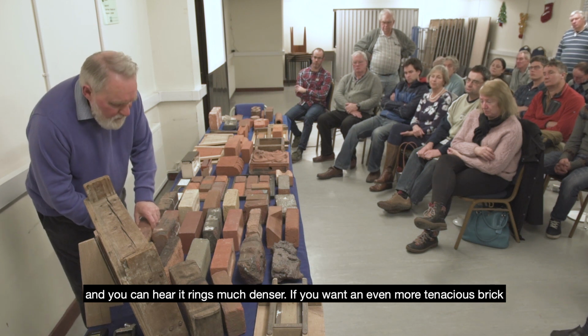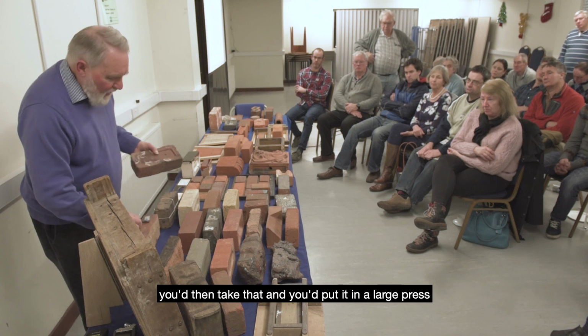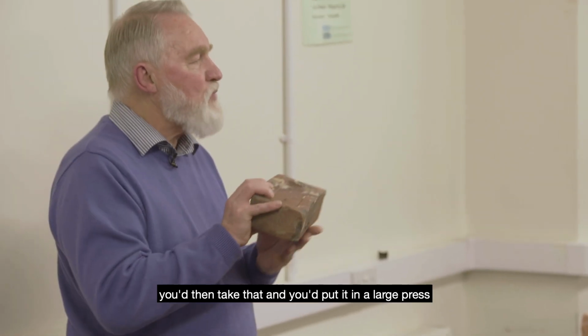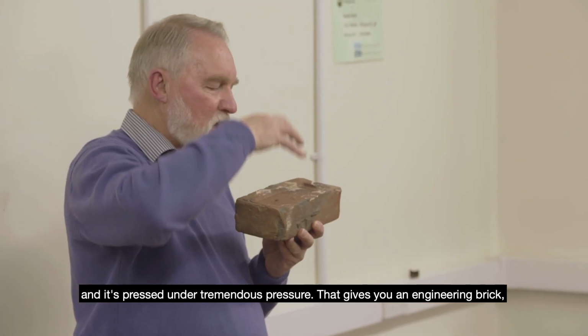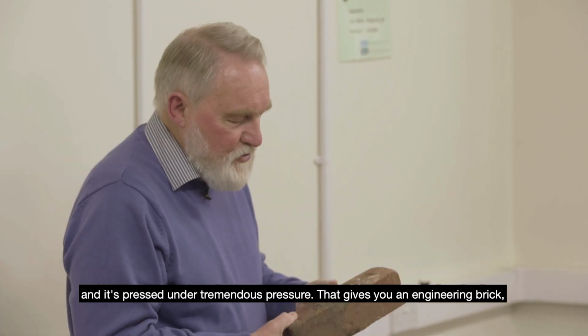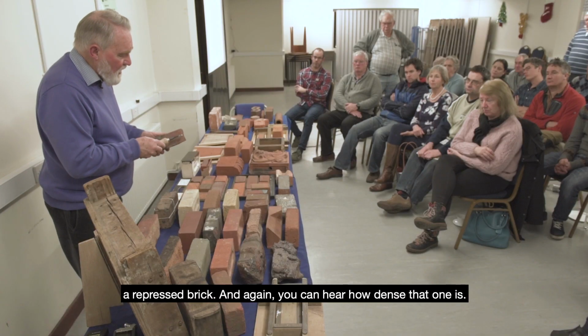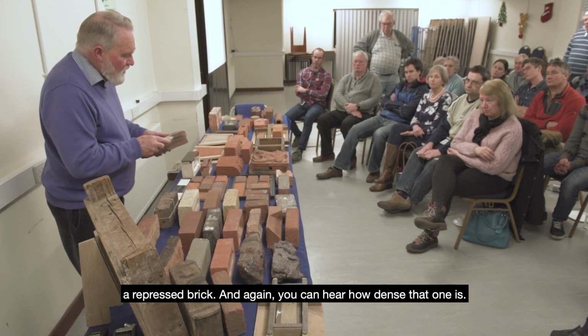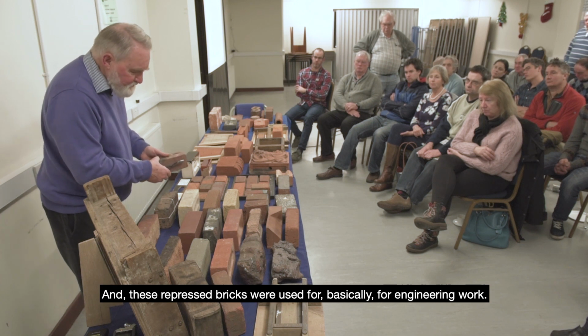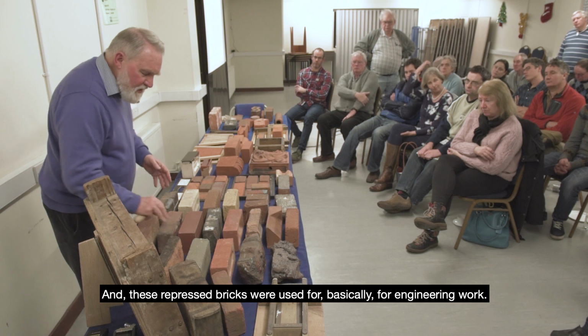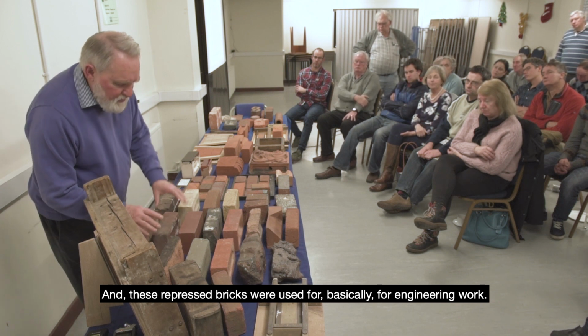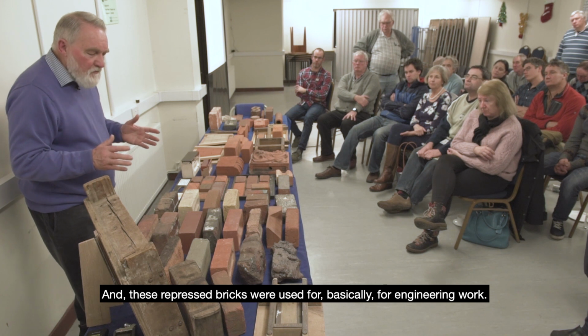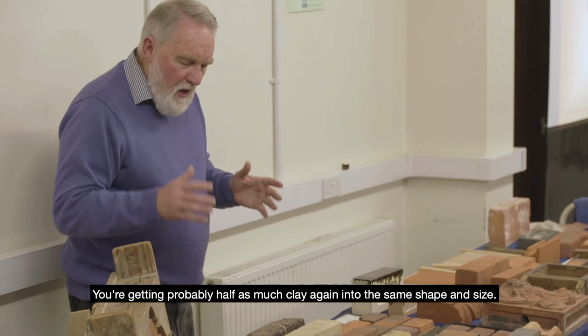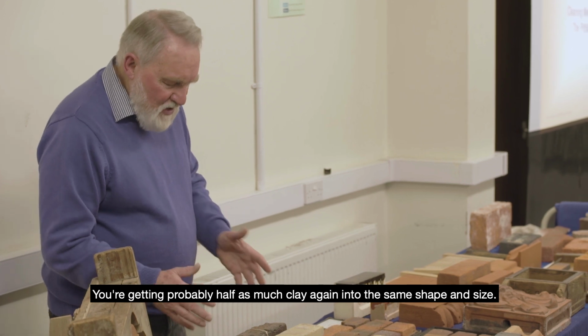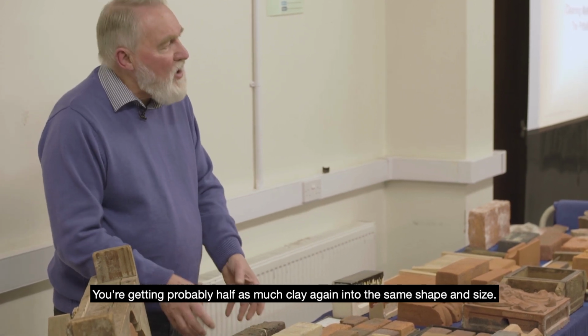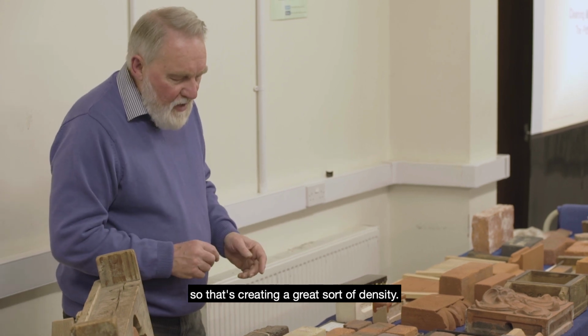If you want an even more tenacious brick, you then take that and you put it in a large press, and it's pressed under tremendous pressure, and that gives you an engineering brick, a repressed brick. And again, you can hear how dense that one is. These repressed bricks were used basically for engineering work. You're getting probably half as much clay again into the same shape and size, so that's creating a great density.